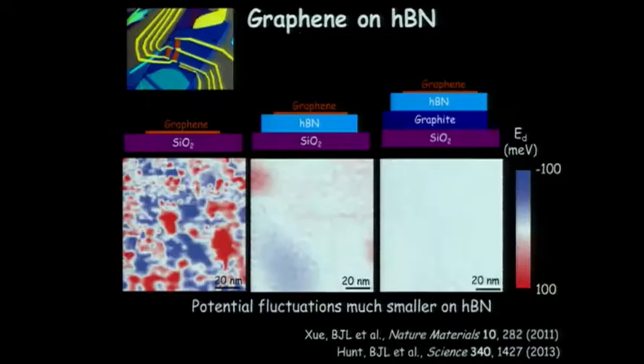And so we did that for a series of different samples. So this is a graphene on silicon oxide on the left-hand side. In the middle, we've put in a 15 or so nanometer piece of boron nitride. And in the right-hand side, we've put boron nitride with a graphite gate and then silicon oxide underneath. And so the color scale here is giving you the fluctuations of this Dirac point, these potential fluctuations. And so this is a typical silicon oxide sample here on the order of about 50 meV fluctuations in the Dirac point. If you move to having the boron nitride, it's reduced by about a factor of 10, but the